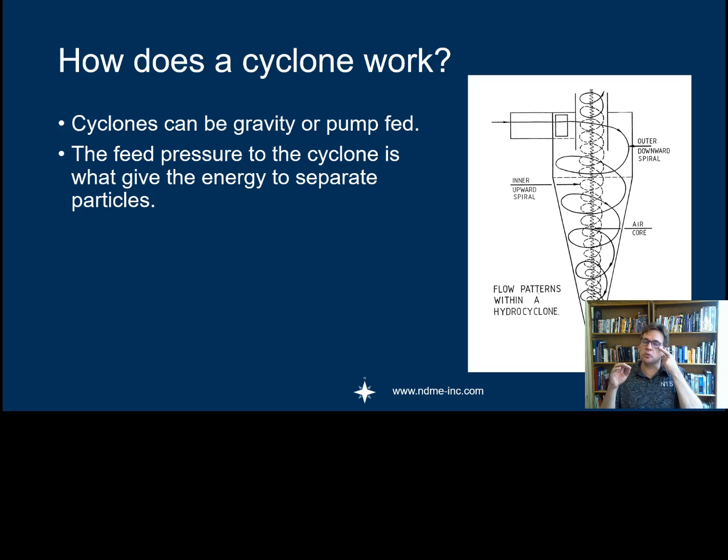And the smaller particles literally get dragged by the centrifugal force, by the water. Typically on the overflow of the cyclone, which is illustrated over here, you have the largest opening, and literally the water almost gets sucked out there. So you can imagine the smaller particles, because of their large drag around them, a lot of surface area per weight, get dragged into the overflow, and the underflow, basically the larger particles, go to the bottom.